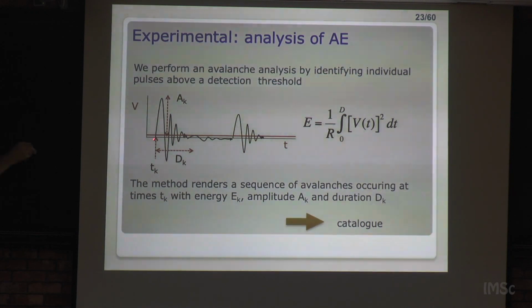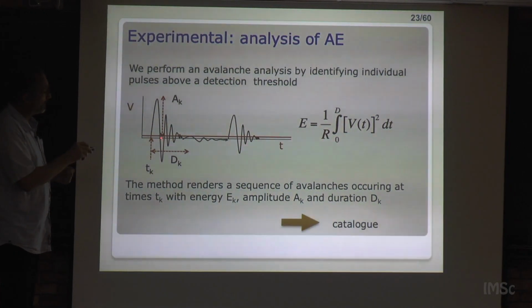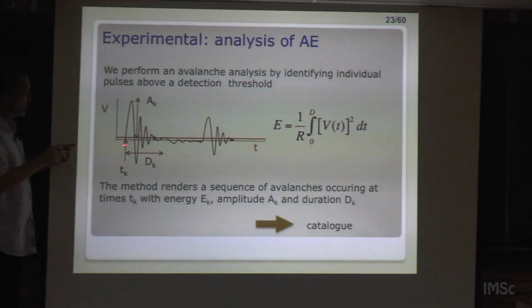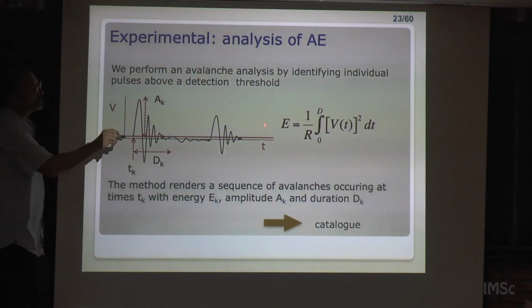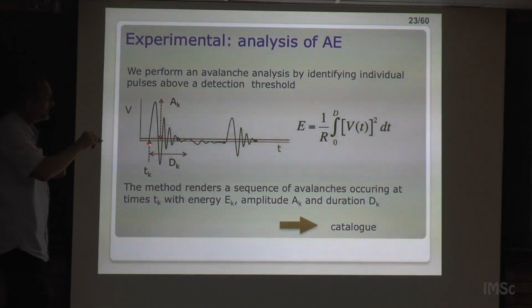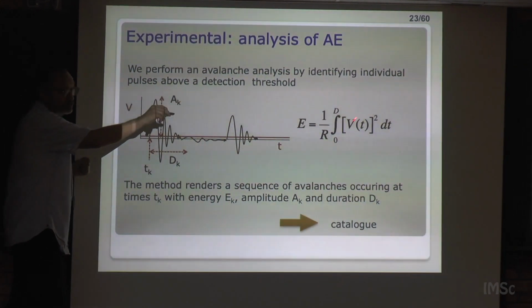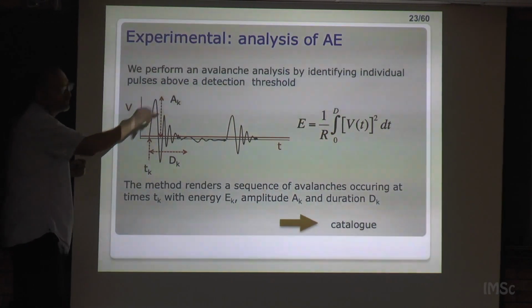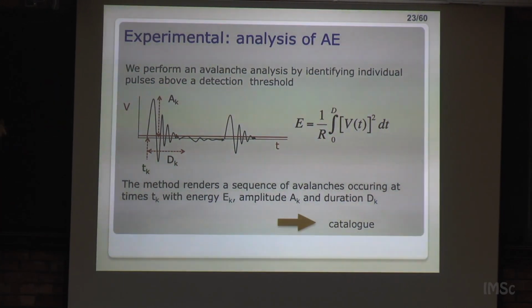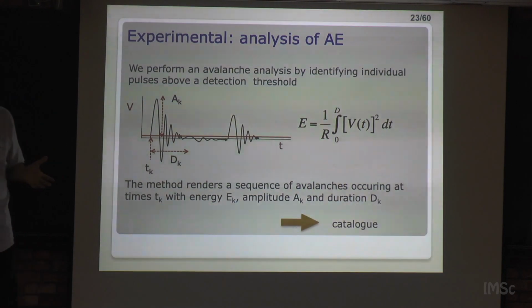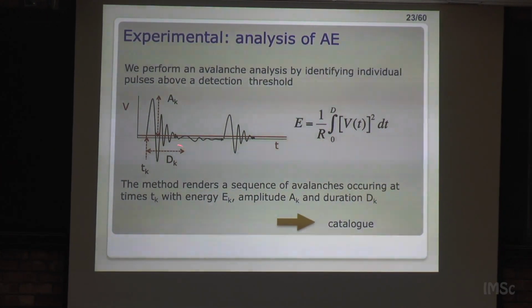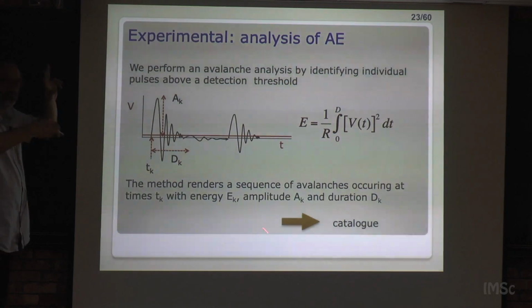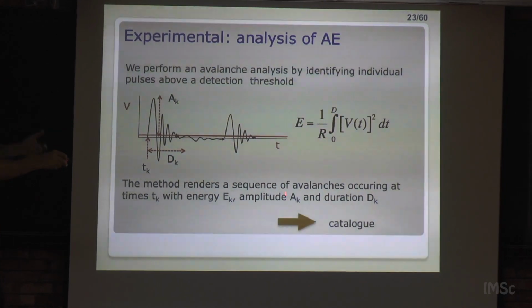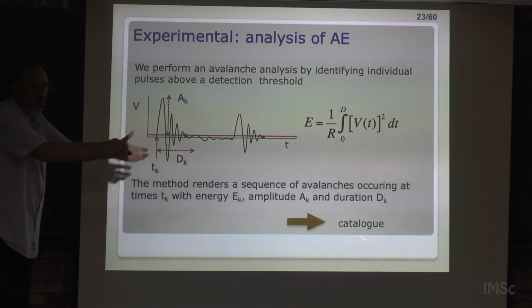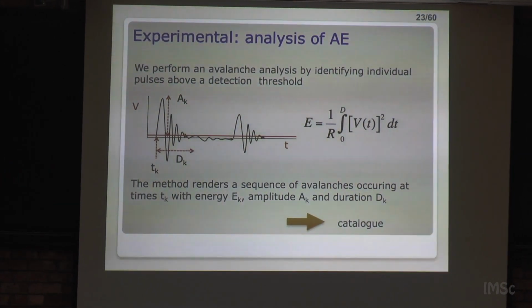Then from this signal, we can measure the starting time. We can measure the amplitude, which is the highest voltage. We can measure the duration. And we can also measure the energy by integrating from here to here. We integrate the square of the voltage divided by the reference resistance, and we get an energy. So at the end, from our train of signals, we get a catalog, exactly as with earthquakes. So we have at time tk an event with energy ek, or amplitude ak, and duration dk. That's the catalog that we will compare with earthquake data.